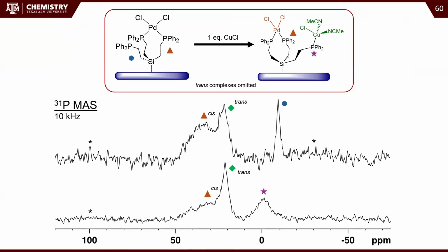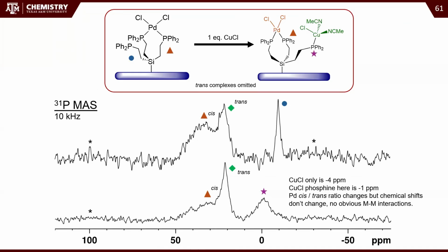So we took this material and we added one equivalent of copper, and that goes pretty much how we'd expect. It does move from a -3 or -4 to about -1. It's a different complex too. Phosphine copper complexes are all kind of not great chemical shift, and they kind of exchange a lot. And so that's within the region that they should be. So it looks okay. No big metal-metal interactions that would drastically change the chemical shift. No big surface interactions that we can see. So far it looks okay.